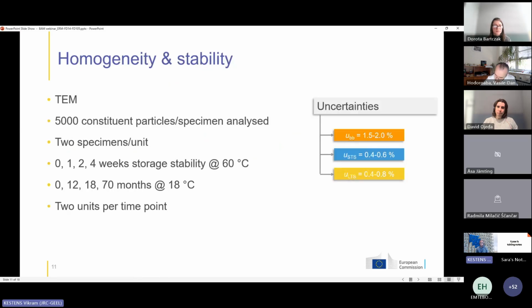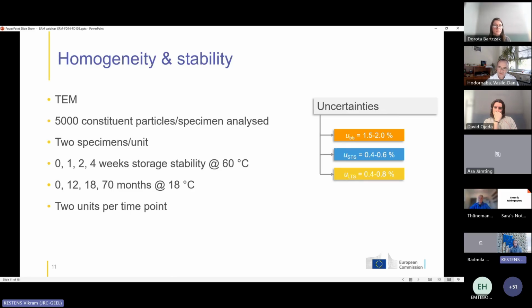We used the electron microscopy results for both homogeneity and stability testing. I will go very quickly over this slide, just to indicate that here we measured even more particles per specimen, so 5,000 instead of 1,000, just to make sure that the measurement uncertainties were as small as possible. We looked at different storage intervals, from 0 to 4 weeks of storage at different temperatures, and we measured 2 units per time point.